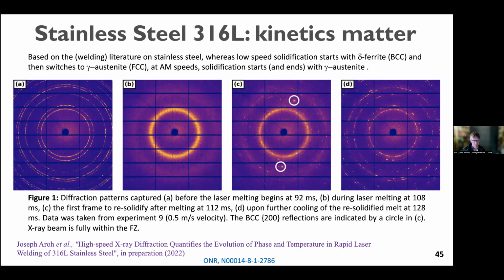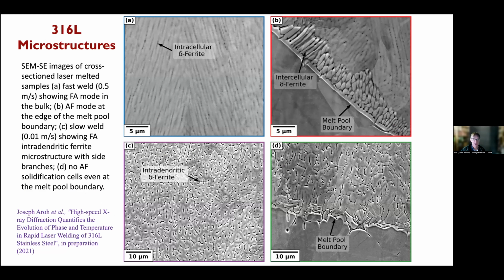The answer is yes. And I'm afraid I skipped over the microstructural evidence. And it is notable, and let me make sure I read these properly. What you see on these two, certainly this one on the top left, was definitely ferrite first and then austenite. On the other hand, if you get austenite first and then ferrite developing, you see this kind of microstructure in the part where it was first coming out as austenite, and then in between is the ferrite, and that's intercellular delta ferrite, and there's definitely microsegregation going on. So absolutely.